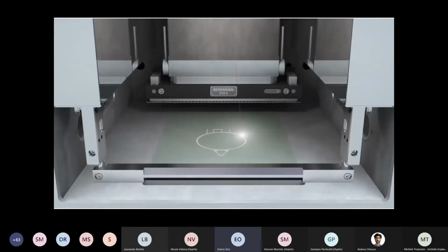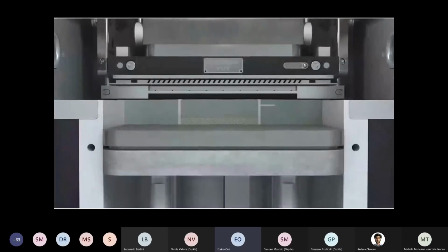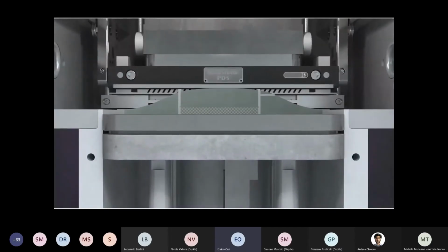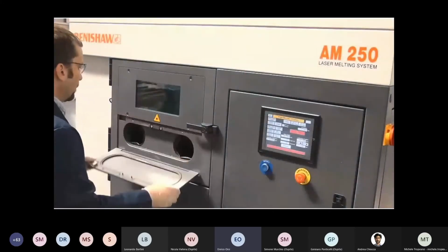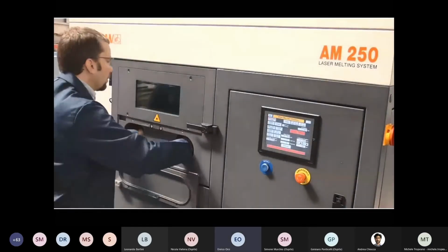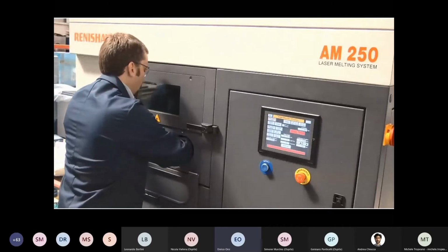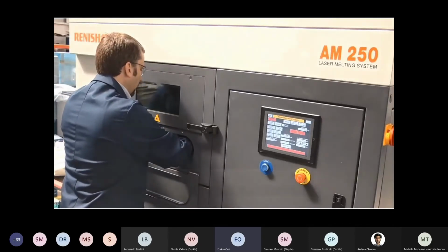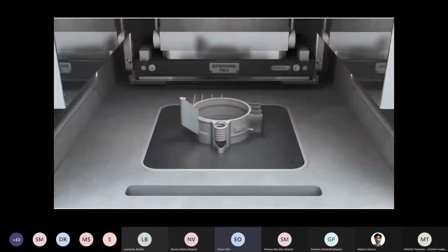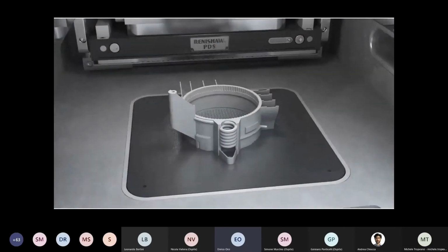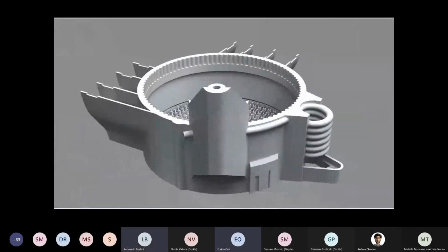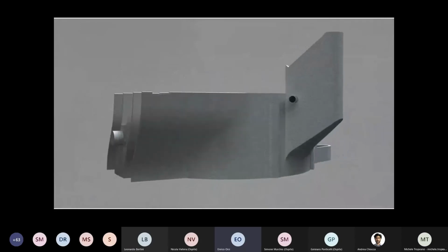So the process continues, and this way each layer is added to the height of the part and will end up in a final metallic device. At the end of the process, the operator, using a glove compartment, cleans out the remaining powder from the machine, sending it to the sieving process, and extracts the plate with the part welded on it.